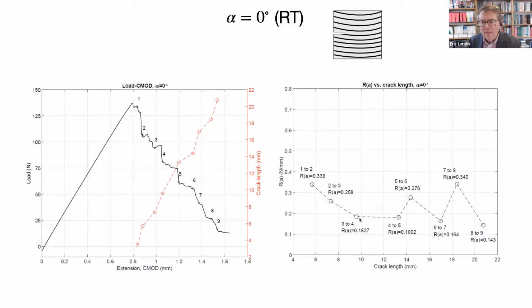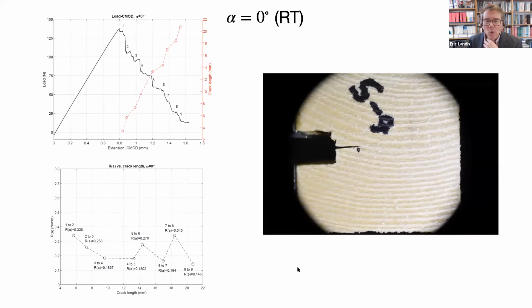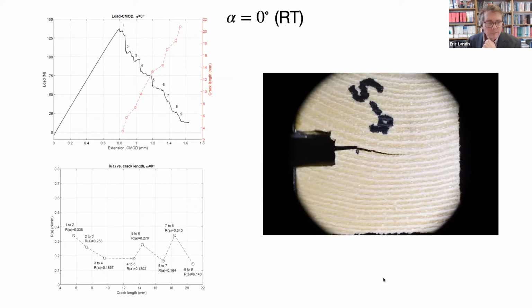Now we do see a fair amount of variability in the crack resistance as the crack grows, although we're not seeing anything that would resemble a rising R curve or a dropping one. Now let's compare this to what we see in the images. So we've got the crack growth from 1 to 2. What I failed to mention before is that, just like in a regular compact tension test, we prime the crack a little bit. We cut it with a little razor to get the crack started. Then as it goes, you see the crack simply follows the early wood.